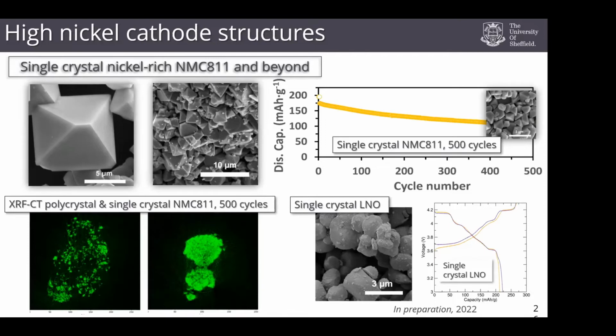This is a very similar experiment to what we did on the Mary Rose. This time we're using fluorescence combined with X-rays. This is showing you some of those spherical materials that we had, these high nickel content cathodes. And after 500 cycles, it's all broken up into little pieces. They tend to fracture, they're put under quite a lot of pressure. This is showing you the same kind of cathode, but now it's a single crystal cathode. And you don't see those dark gaps between the particles anymore because they're not cracking as much. And in fact, you find that you get better capacity retention over many, many hundreds of cycles by using these kinds of morphologies.